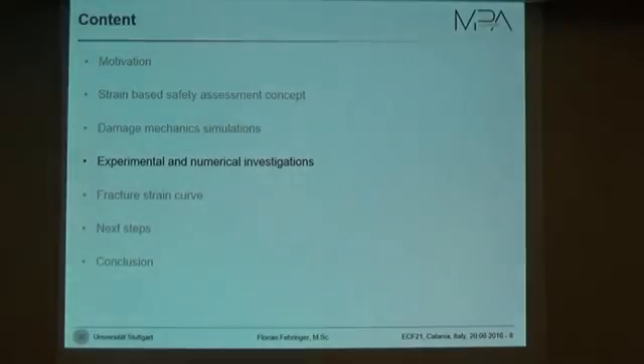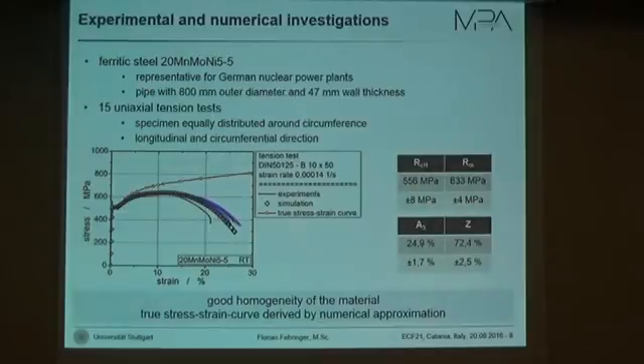The experimental and numerical investigations we did so far. First of all, what's the material we're using? We're using a ferritic steel, representative for German nuclear power plants. And we take all our samples out of a pipe, which has an outer diameter of 800 millimeter and a wall thickness of 47 millimeter.